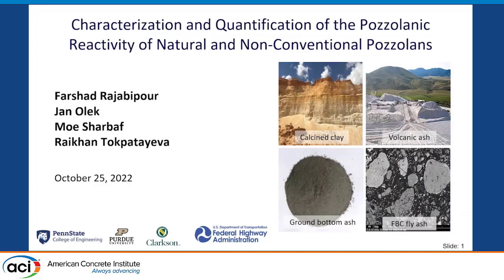This presentation will cover reactivity and alkali release of non-conventional pozzolans — specifically three sources of calcined clays, three sources of volcanic ash (also known as raw natural pozzolans), three sources of ground bottom ash from the same type of utilities as conventional fly ash, and two sources of fluidized bed combustion (FBC) fly ash. These come from a different type of coal-burning utility where coal is burned at about half the temperature — about 800°C — so many non-combustible phases such as clays and quartz do not melt, resulting in a semi-angular and porous nature in the ash.